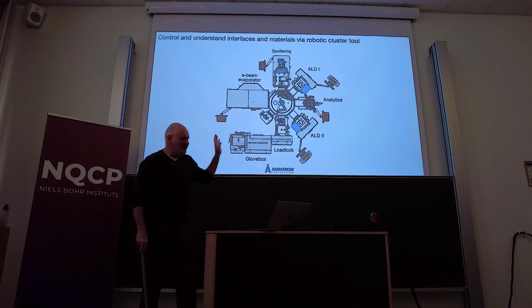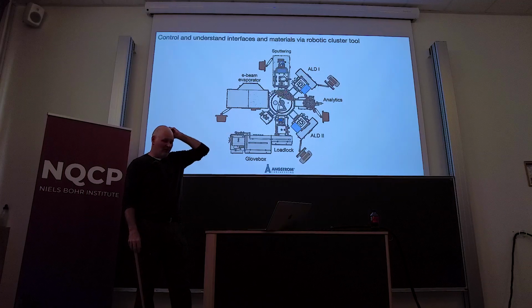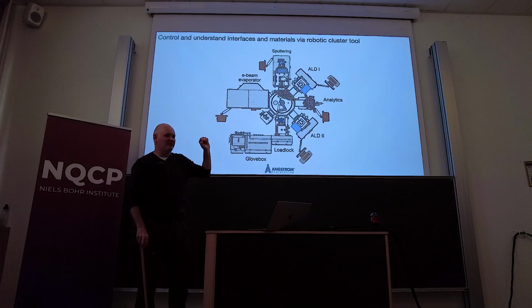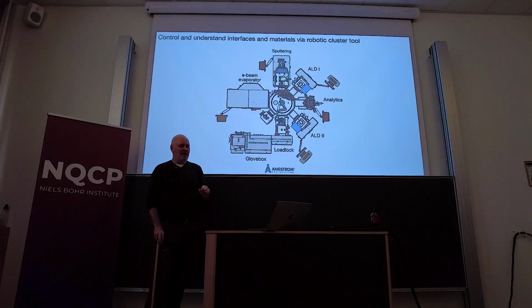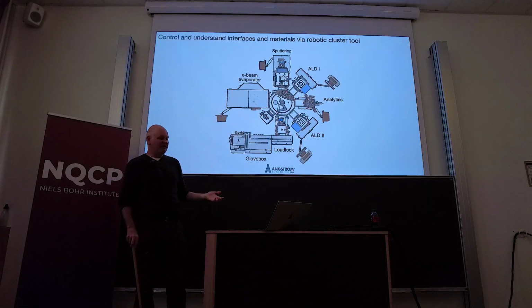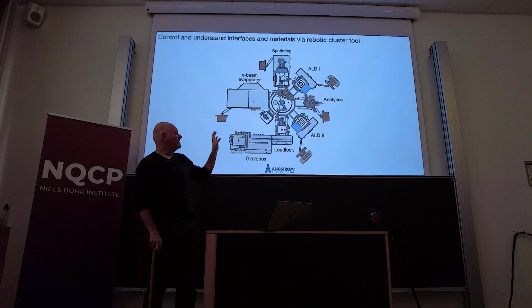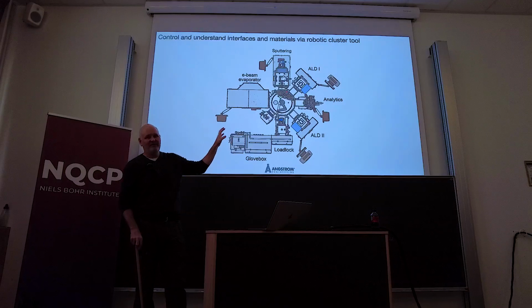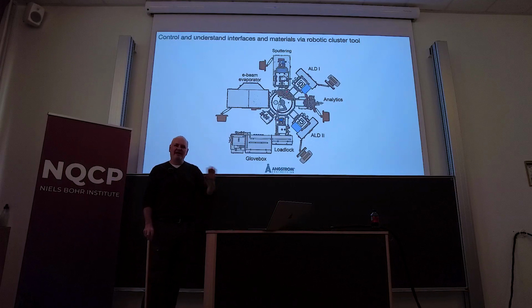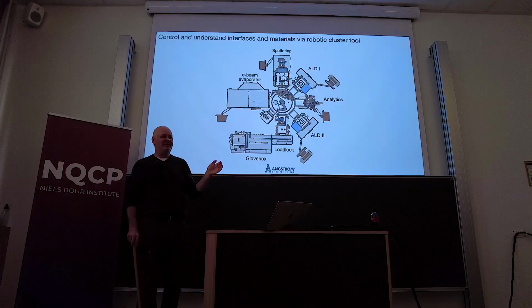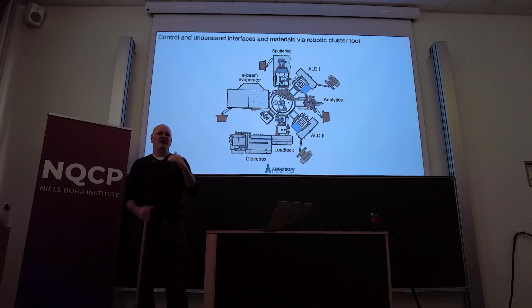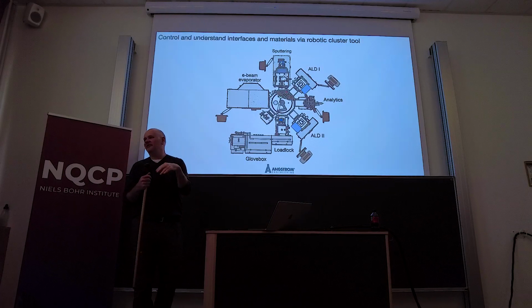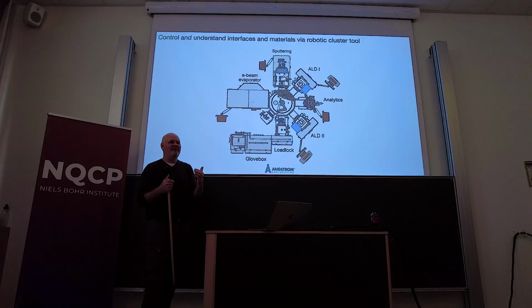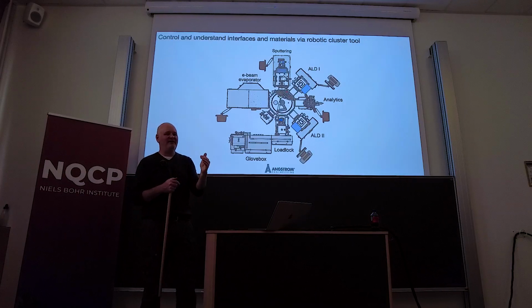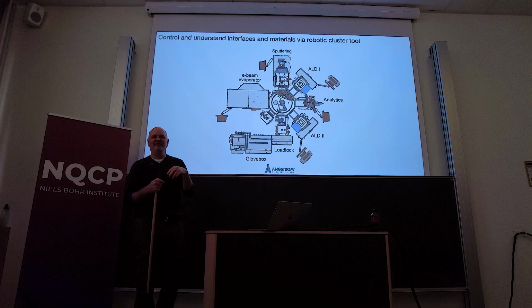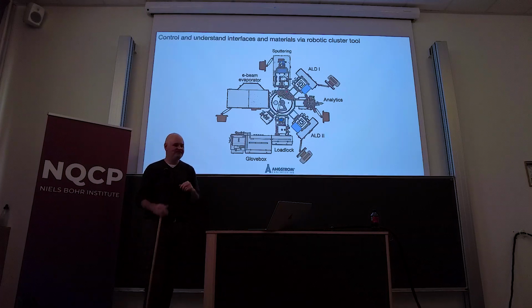Okay, so the ALDs were really there for one, because I'm interested in growing nitrides by ALD. So actually being able to grow the superconductor part of this by atomic layer deposition, but then having an oxide chamber so that we can do dielectric spacers, but then also passivation layers over the surfaces to protect from growing non-specific oxides on the surface. So we can decide, I want 1 nanometer of aluminum oxide, and I'm going to live with the loss of that, knowing that it's going to be less than the loss of whatever random niobium oxide that grows.